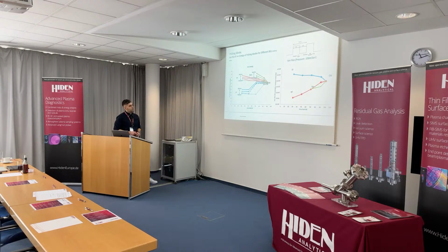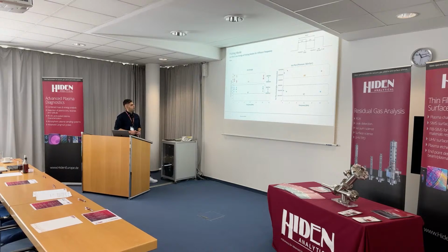And this is the effect of duty cycle on ion flux. So the LF pulse has a decrease in ion flux, HF pulse increases, and sync pulse also increases. This is the effect of frequency on ion energy and ion flux for HF pulse and LF pulse. As the frequency increases, the ion energy almost remains constant and ion flux almost remains constant. So the frequency doesn't have so much effect on the ion energy and ion flux in different pulsing modes for argon plasma.